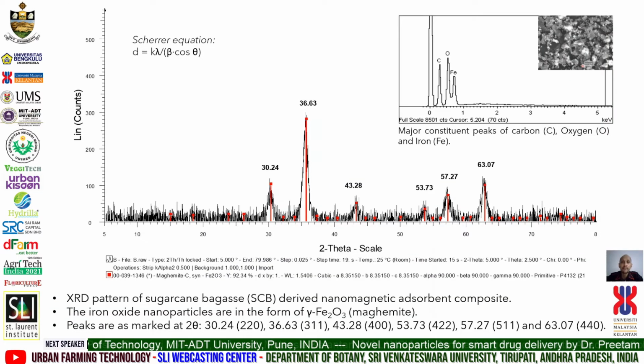An example of an XRD spectrum for sugarcane bagasse derived nanomagnetic adsorbent composite is shown here. The iron oxide nanoparticles were in the form of maghemite. The sizes of the nanoparticles can be estimated from the XRD data using the Scherrer equation, which gives a relationship between particle size and peak broadening by the given equation, where d is the particle size of the crystal, k is the Scherrer constant, lambda is the X-ray wavelength, beta is the line broadening in radians obtained from the full width at half maximum, and theta is the Bragg diffraction angle of the XRD diffraction patterns. EDX analysis also revealed the major constituent peaks for carbon, oxygen, and iron.